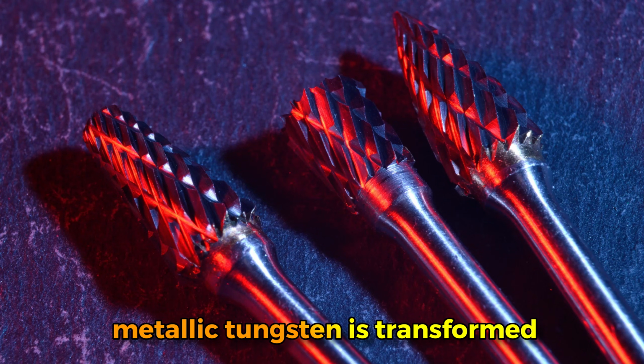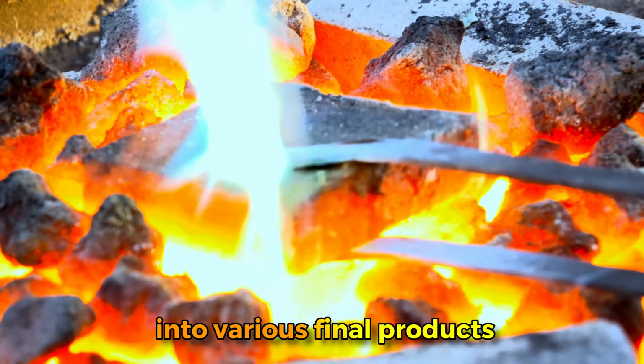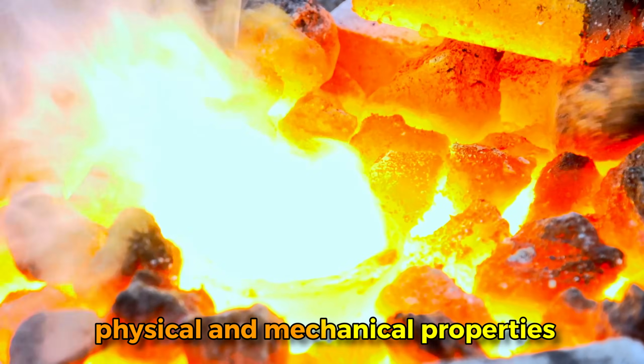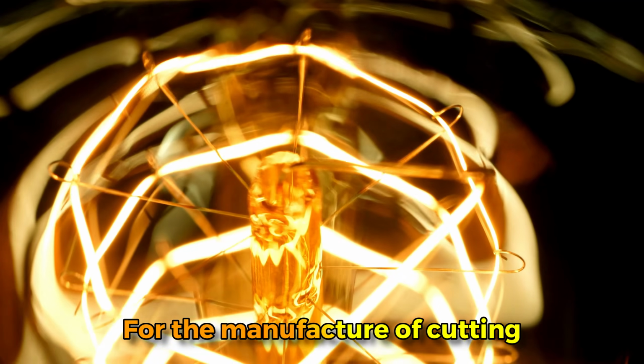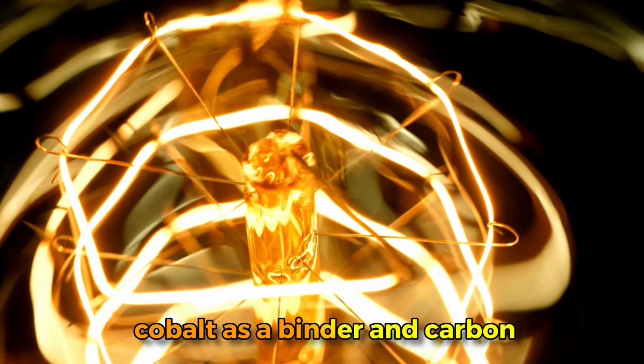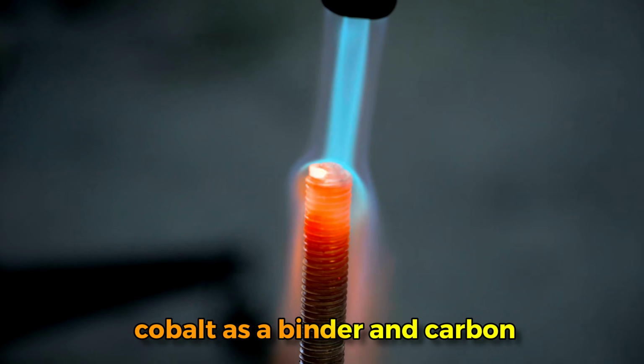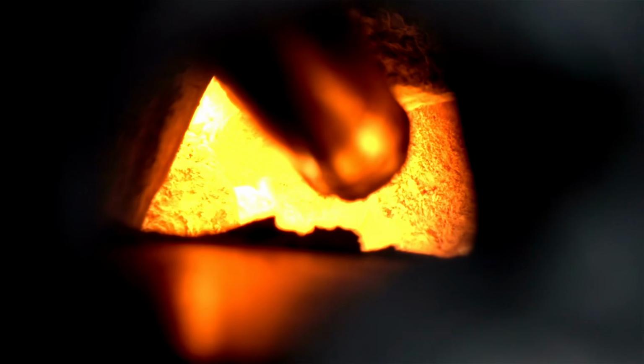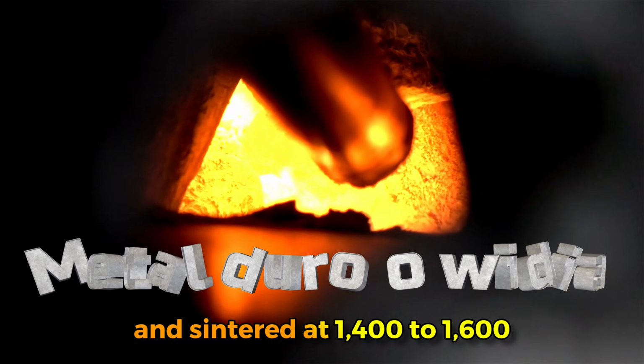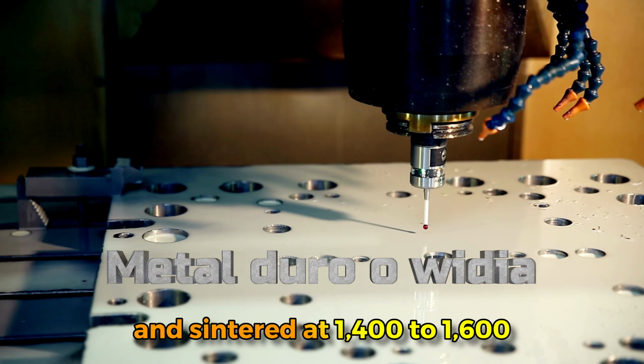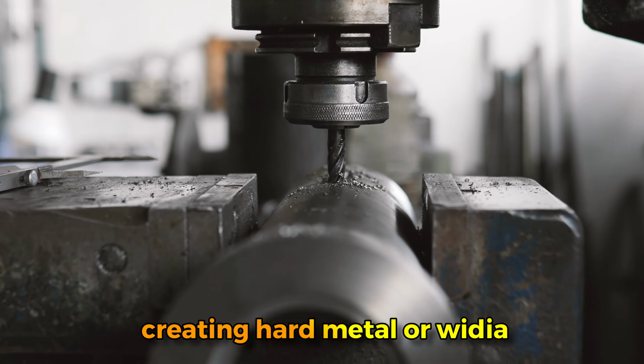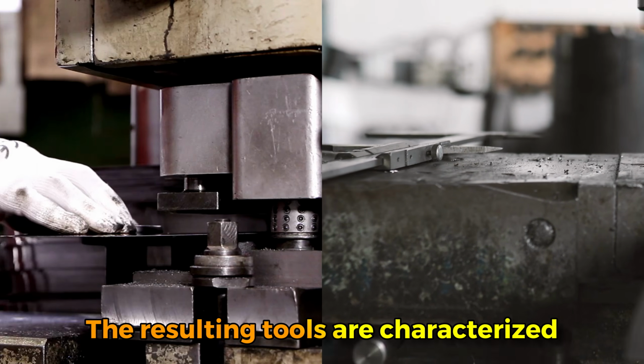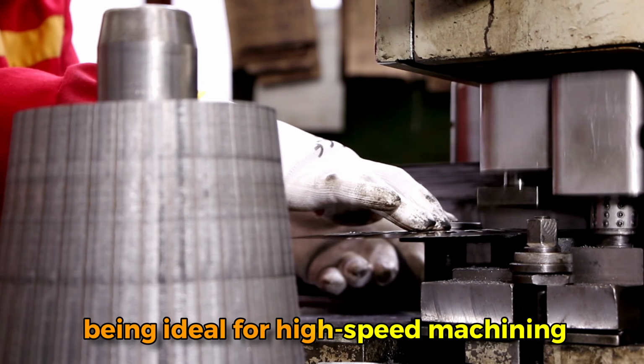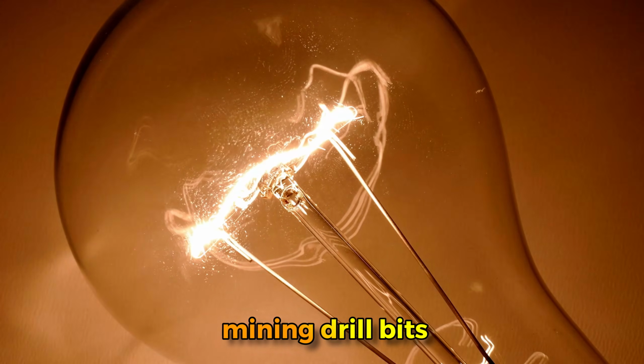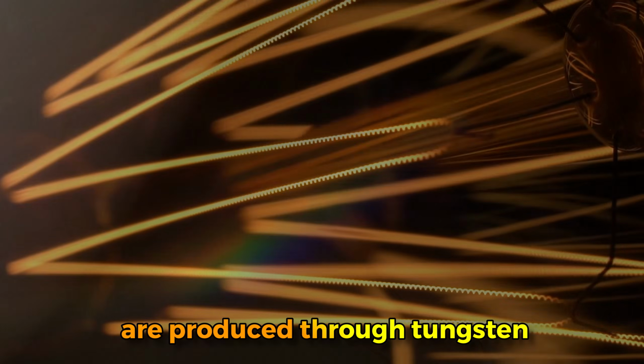Once refined, metallic tungsten is transformed into various final products, taking advantage of its exceptional physical and mechanical properties. For the manufacture of cutting tools, tungsten powder is mixed with cobalt as a binder, 6 to 15%, and carbon to form tungsten carbide, WC. This mixture is pressed into molds and sintered at 1400 to 1600 degrees Celsius, creating hard metal or Widia. The resulting tools are characterized by their extreme hardness and wear resistance, being ideal for high-speed machining, mining drill bits, and forming dies.